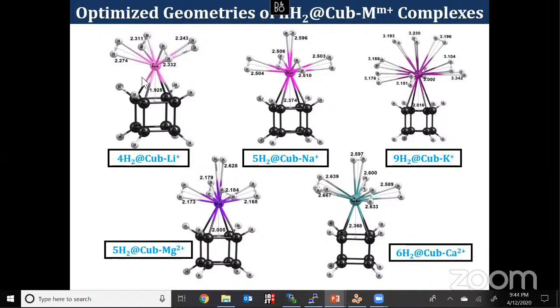First I figured out where the metal ion binds tightly with the substrate. Then I put hydrogen molecules on one by one. From the optimization results, I found that lithium cation can absorb a maximum of 4 hydrogen molecules, sodium absorbs 5, and potassium absorbs 9. When we move from lithium to potassium, the ionic radius increases and the van der Waals radius of the metal atom increases. That means we get more room to accommodate hydrogen molecules.